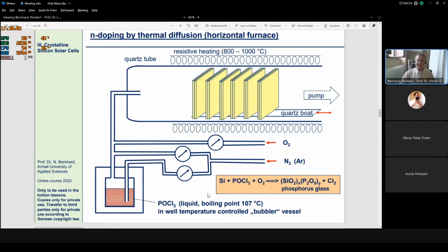This is done in such a quartz tube, which is heated up to 800 to 1000 degrees centigrade. The wafers are in a quartz boat. As I mentioned already, they can be either back to back, or they can also be in a single arrangement. And then we use three gases. One is oxygen, one is a carrier gas, which usually is nitrogen, but also could be argon. It's a gas which really does not participate in the reaction. And the last one, it's not a gas, it's a liquid.